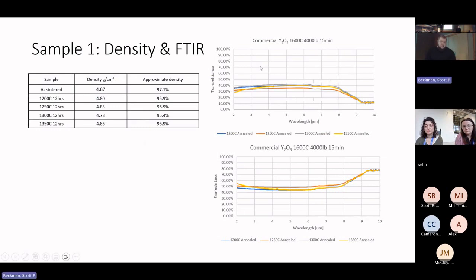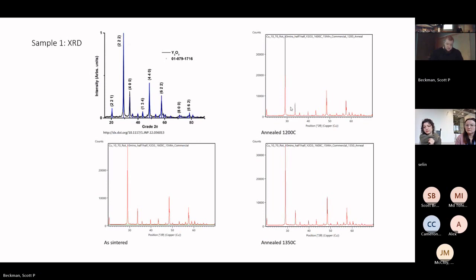And we found here that we were able to achieve right around 35 to 40% transmittance, varying a little bit depending on the annealing conditions, which corresponds to an approximately 50% loss from the ideal condition of transmittance.